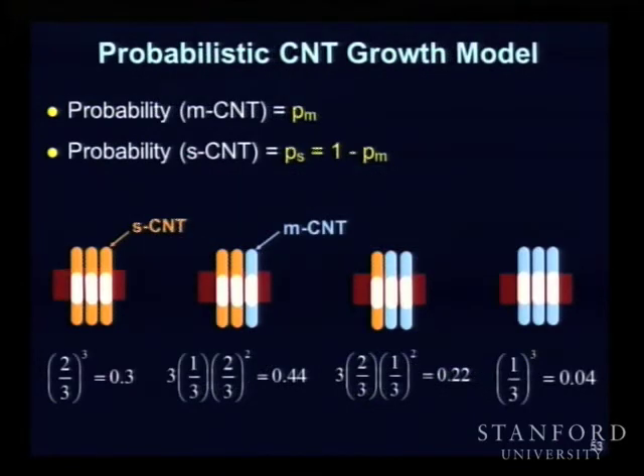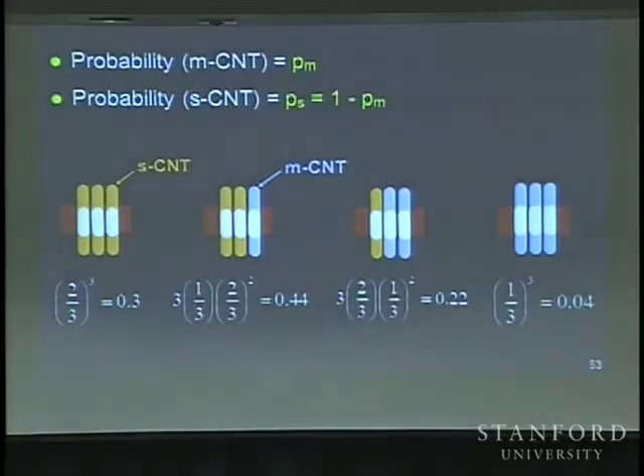So let's take a probabilistic carbon nanotube growth model, right? When you grow carbon nanotubes, there is a certain probability PM that a carbon nanotube is a metallic carbon nanotube. People would typically tell you that PM is 1/3 or 33%. There have been growths that people demonstrated where the PM is 10%. That's great, but still there is a non-negligible fraction of these carbon nanotubes that will be metallic, and the remaining carbon nanotubes will be semiconducting, which is 1 minus PM.